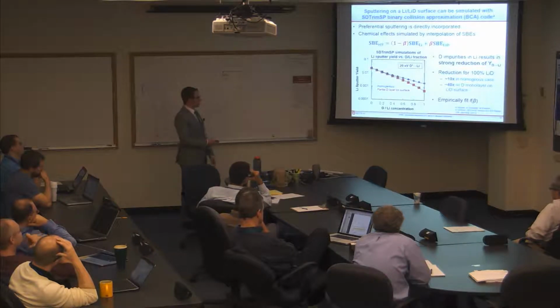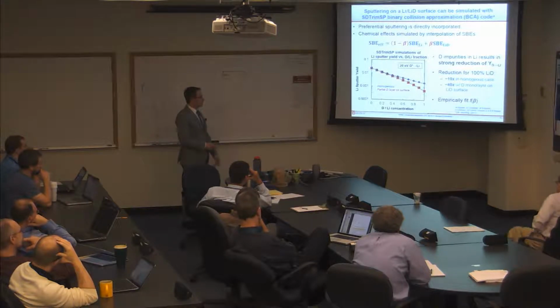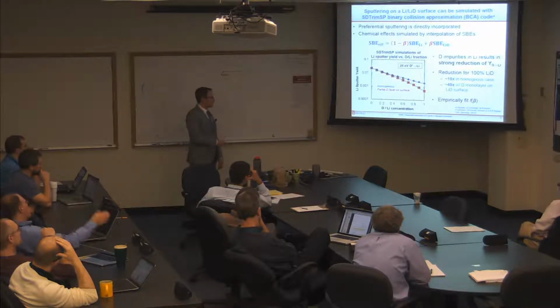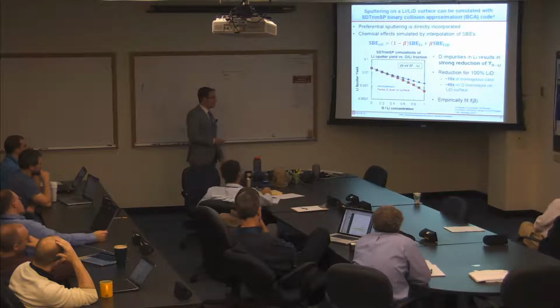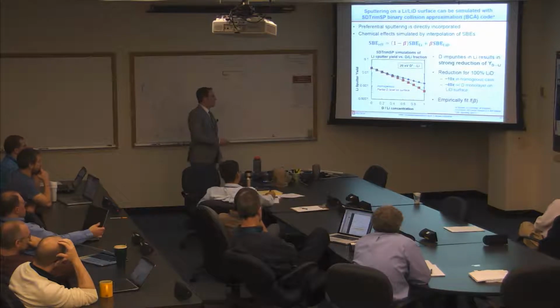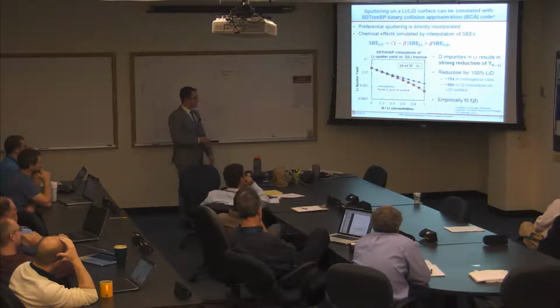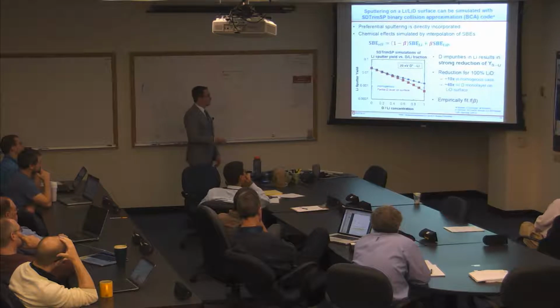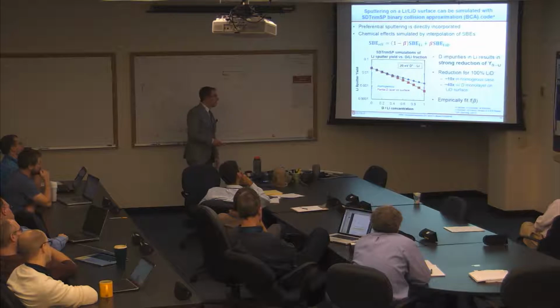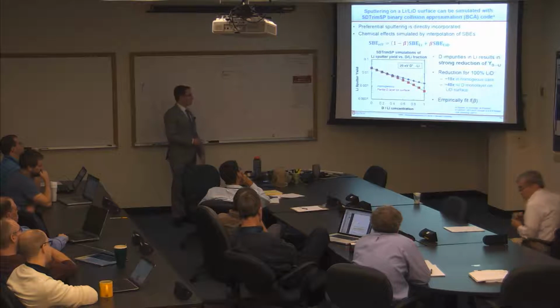And the blue curve is the lithium sputtering yield as a function of the deuterium to lithium concentration. The blue curve is that homogeneous case that I talked about on the last slide, of no deuterium adsorbing on top of the lithium. And then the red curve is when you actually have a deuterium layer forming on top of the lithium surface. And so this implies very strong reductions of the sputtering yield. You expect a reduction of about a factor of 10 in the homogeneous blue case, and a reduction of about a factor of 40 in the case of a deuterium monolayer on top of the lithium deuteride surface.